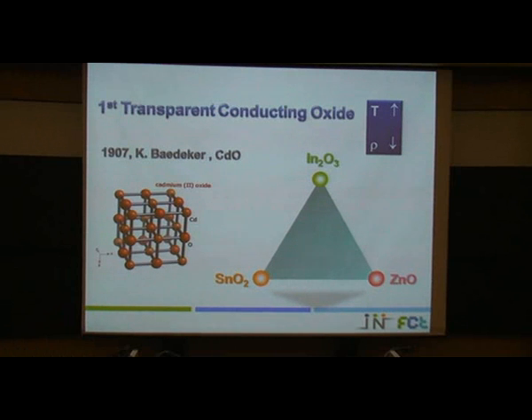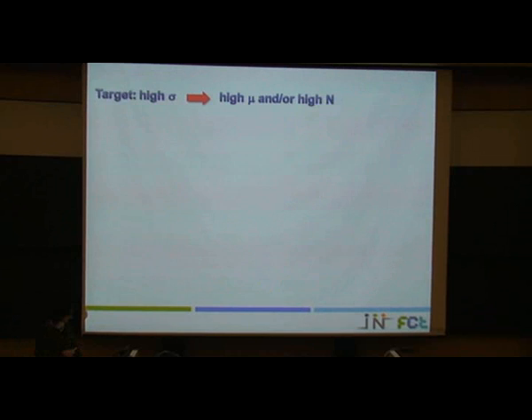done more or less 100 years ago by Baedeker, and it was cadmium oxide. Of course, for this type of material, we want a high transmittance and simultaneously a low resistivity. Those are the properties we want for a transparent conducting oxide. Today, most of the TCOs are based on this system: indium oxide, tin oxide, and zinc oxide. ITO is between indium oxide and tin oxide. But since indium is expensive, we are looking today for other materials, and especially zinc oxide works very well and is a good alternative to indium oxide.